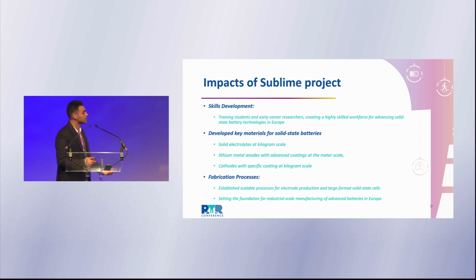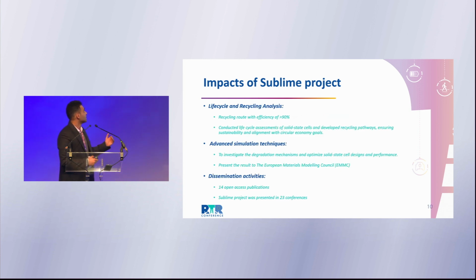A lot of students were trained, and a lot of knowledge was obtained by processing these materials. We developed materials at kilogram scale: solid electrolyte, cathode, lithium metal anode. This electrode we fabricated, and life cycle analysis. We developed a recycling path with 90% efficiency, and simulation techniques. For example, the final results were presented to the European Materials Modeling Council. And at the end, we published 14 open access publications and presented the results in 23 conferences.